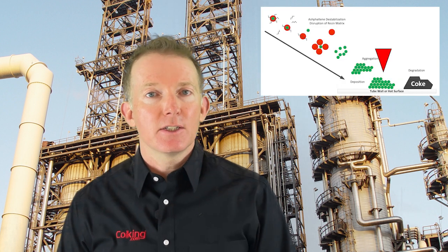I'm thinking about two areas in the delayed coker in particular. One of which is in various heat exchangers. We have preheat exchangers in our unit. Almost everybody has them. And those are exchanged with heavy gas oil predominantly, where there is the potential to form coke over very long timescales, because the time and temperature is sufficient at those internal heat exchange surfaces where very mild cracking reactions can actually happen.